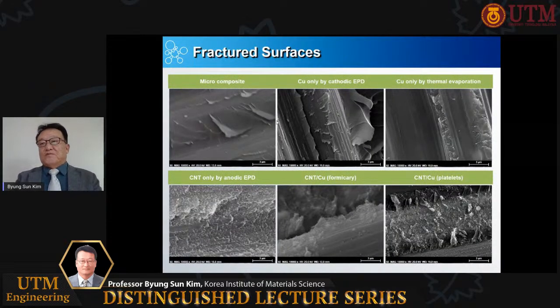This is the morphology of the fracture surfaces of nanocomposites compared with microcomposite. The fracture surface of the microcomposite is quite smooth compared with that of all nanocomposites. Fracture surfaces of all nanocomposites show deposition traces of CNT as well as copper. However, the bottom three are showing more depositions of CNT and copper respectively. CNT copper depositions are seen on the fracture surfaces of formicary and platelet nanocomposites, while only CNT is deposited on CNT-only nanocomposites. These fracture surfaces may explain that the bottom three composites' electrical conductivity and interlaminar shear strength have relatively higher values.